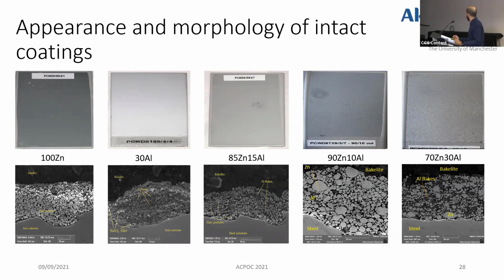Okay, one last question maybe before coffee, Yanwen. Okay. I just wonder about the role of aluminium: if it is only filling the volumes, can we change aluminium to talc or kaolin and have the same action? Because if you put more aluminium, it looks like the conductivity is reduced. So I don't think the role of aluminium is to increase the conductivity. It might be only filling the volumes. Probably talc and kaolin are cheaper and can act with the same function. Yeah, that's what I thought before. But as I said before, for longer immersion time, the pH of the medium is increasing. And I think the pH inside the coating is much higher than the medium. It reaches about 8, which is the value at which the passivity of aluminium starts to be destroyed, and it may offer the galvanic action and connection at that time.